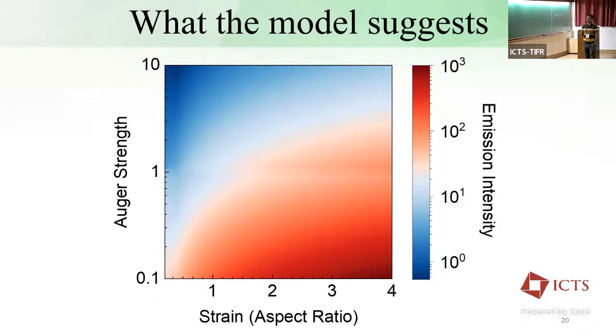And we did a bunch of calculations which I am not showing here, but there is another problem here, by the way. It's good to have a lot of excitons here, because it acts like a reservoir, and your reservoir ideally should be an infinite supplier, right? But the fact that you are forcing many excitons to come close by, there is a very strong exciton annihilation that happens, and this is just the Auger process, right? Because of that, you tend to reduce this exciton density right on top of the pillar, and that's a bad thing.